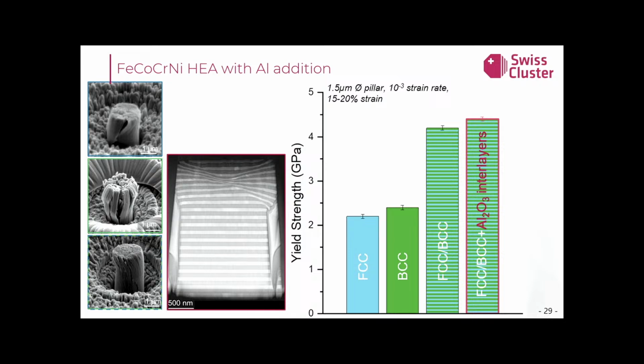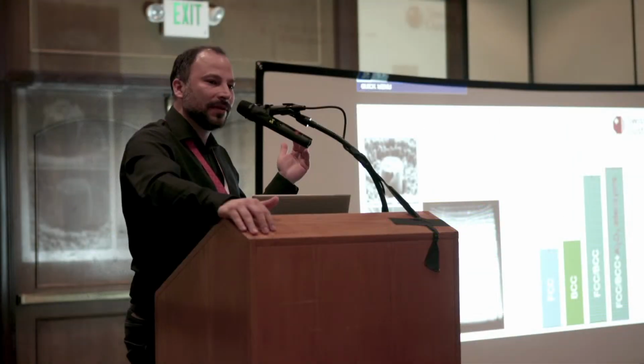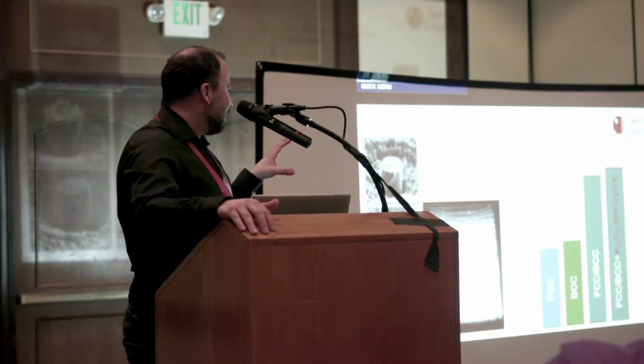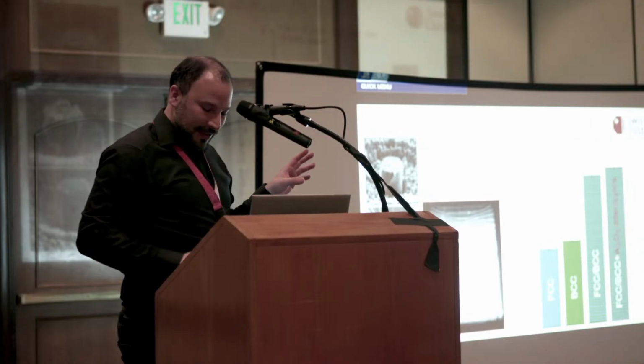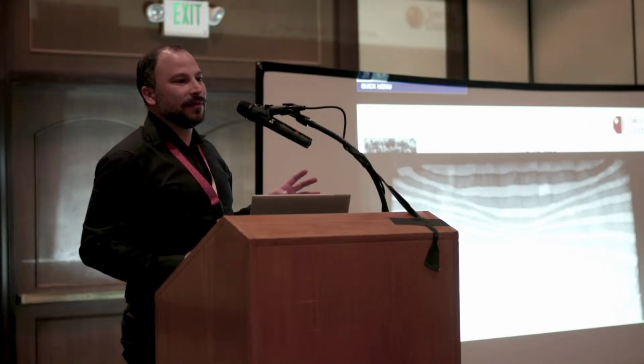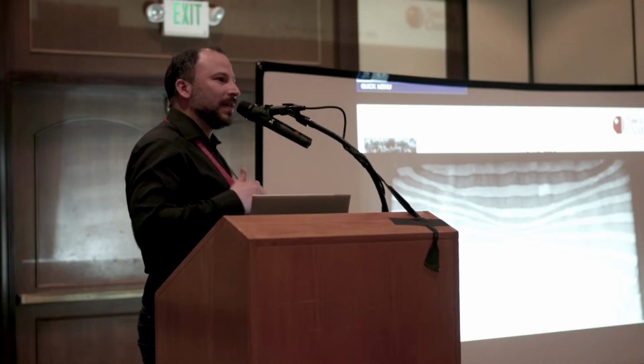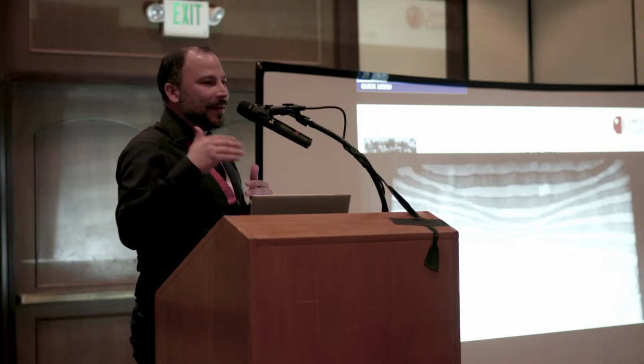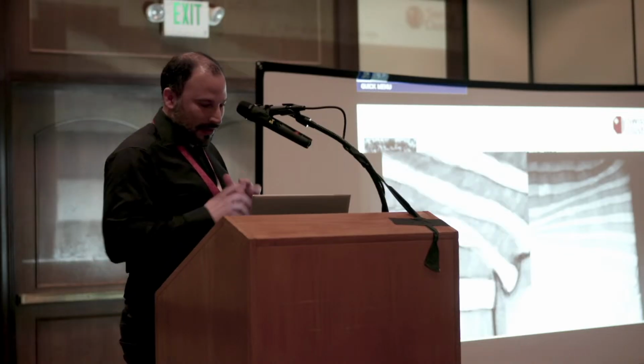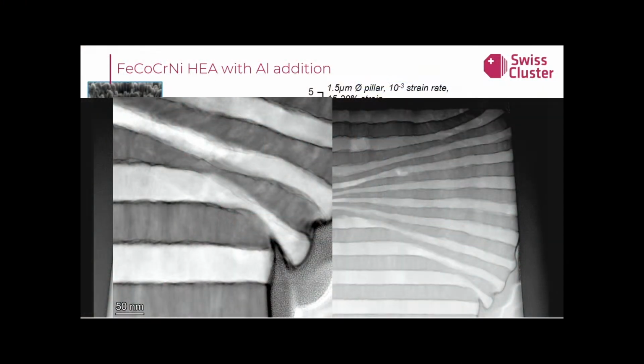So yes, with the combination or the introduction of these aluminum oxide layers, we see that there is not only an increase in the yield strength of the material, but there's also this very nice effect of having a very plastic deformation. So this is a way to obtain a very hard material that has a very plastic behavior, right? In a zoom-in TEM image of the post-mortem pillar, we see that there's no crack in this pillar, right? So we really have a very plastic effect in this type of system.